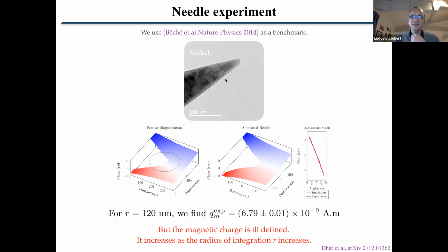But the thing is, with this kind of approach, you don't have a well-defined magnetic charge, because this radius here, if you increase the size of the radius, you will include more and more material, more and more magnetic moment. And by increasing more and more magnetic moment, you will increase the value of the magnetic charge. So the value of this magnetic charge here is not unique. It's dependent on the value of the radius, which means this magnetic charge is really a pseudo-magnetic charge, is ill-defined, and that's really not a proper magnetic monopole. But still, it was a very nice experiment done by Béché and collaborators there.